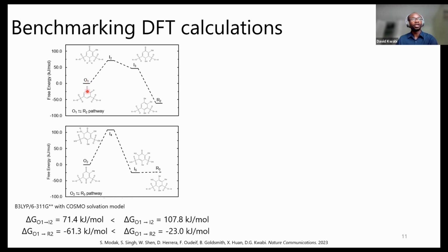And long story short, what we found is that the overall free energy for adding water in the first step is actually much more negative than the second step. So that sort of agrees with our experimental data. And again, the very first elementary step where we add water to the molecule is much more exothermic, if you like, or has a lower energy barrier in the first step versus the second step. So both of these observations are qualitatively consistent with what we've observed by experiment.